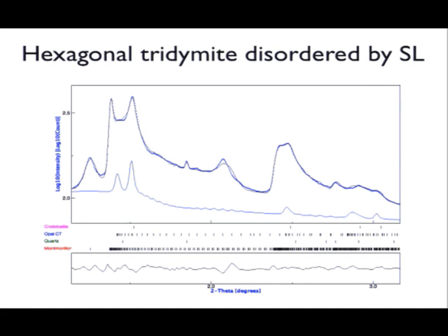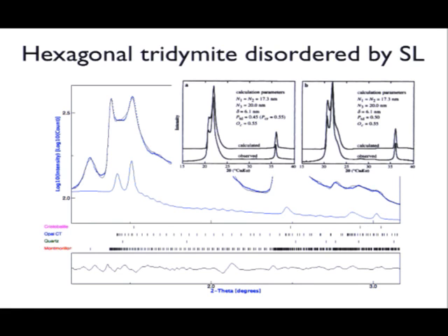And actually, we then tried to see if our model was really similar. This peak looks similar to the peak of theirs, although they had much more broadening due to the fact they had smaller crystallites. So the second peak and the third one, and here is the third one, so we get the same intensity. Actually, as you see this oscillation, these come from the single layer model and depend on how much you choose for the supercell.